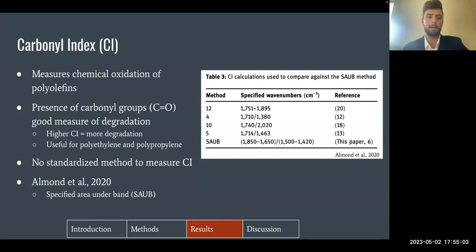Unfortunately, there is no standardized method to measure the carbonyl index. Table 3 to the right is from Almond et al. 2020, who compared and contrasted different methods of calculating the CI and proposed a method called the standard area under band, or SAUB method, as seen at the bottom of the table, to calculate it more accurately. There's no need to pay too much attention to the other method numbers on that table, but the SAUB method was chosen for this experiment in the hopes of obtaining accurate CI measurements in the masks.